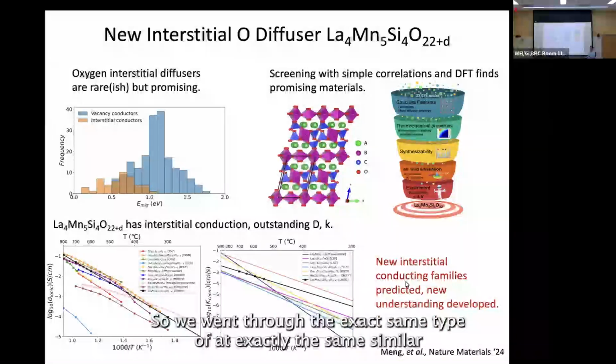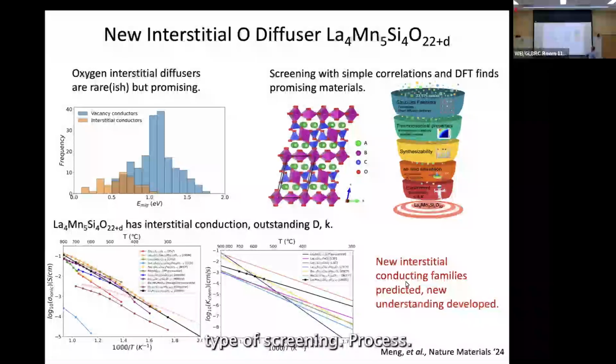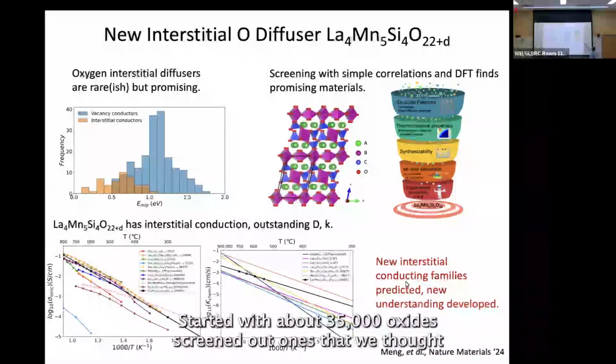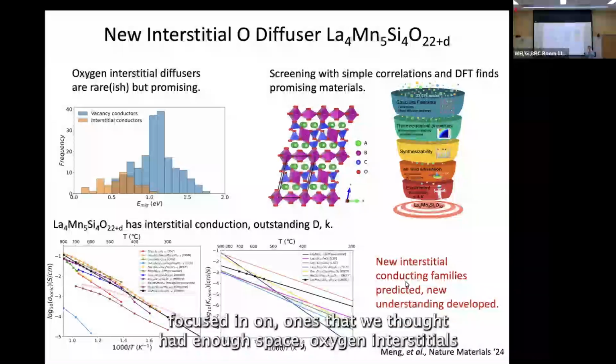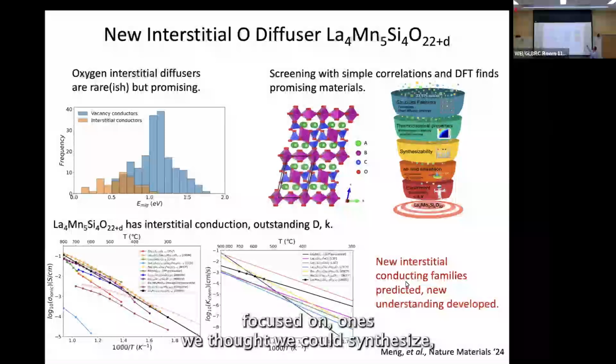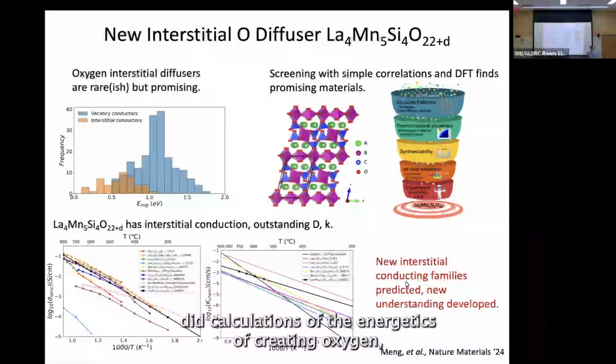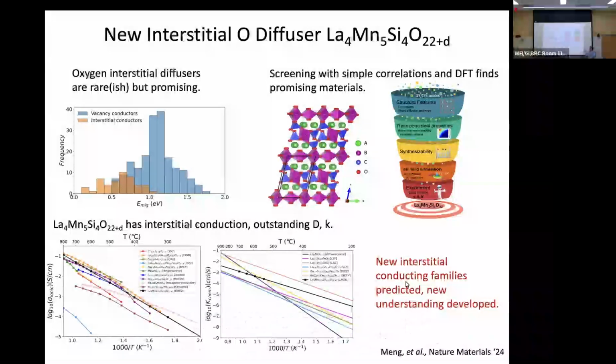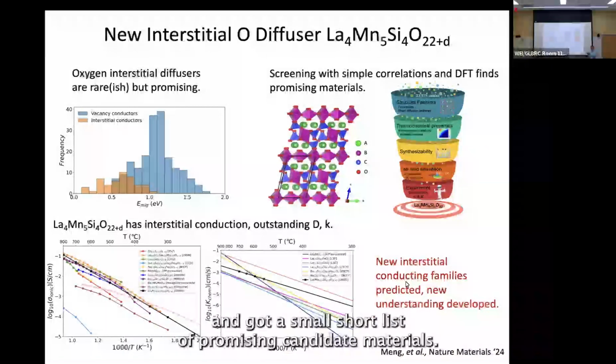So we went through a similar type of screening process. We started with about 35,000 oxides, focused in on ones that we thought had enough space to form oxygen interstitials, focused in on ones we thought we could synthesize, did calculations of the energetics of creating oxygen interstitials and of moving oxygen interstitials around, and got a small, short list of promising candidate materials.